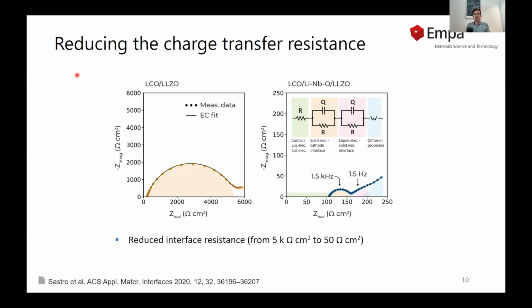We also characterized the charge transfer properties of the interface in the half cells. Here on the left, we have the Nyquist plot of the EIS measurement of the LCO/LLZO half cell without any interface modification. We observe an interface resistance in the order of 5 kilo-ohm square centimeter. On the right, we have the Nyquist plot of the EIS of the interface modified half cell, and we observe that the interface resistance drops to values of only 50 ohm square centimeter. This demonstrates that the interface modification that we investigated, this lithium niobate interlayer, significantly mitigates the formation of ion blocking decomposition products at the cathode electrolyte interface.